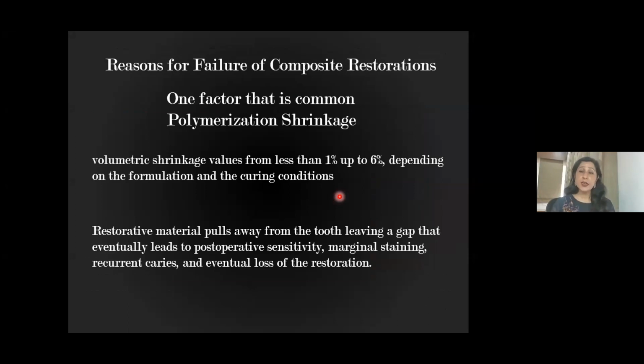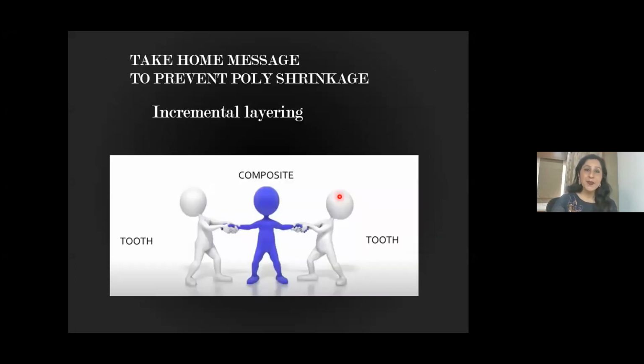Now, reasons for failure. One common factor which is always present in all the reasons is polymerization shrinkage. And this is where the restorative material pulls away from the tooth, leaving a gap that eventually leads to post-operative sensitivity, marginal staining, recurrent caries, and eventual loss of restoration.